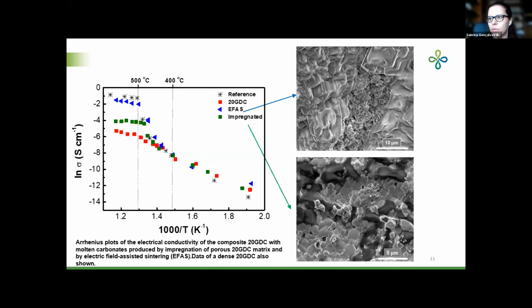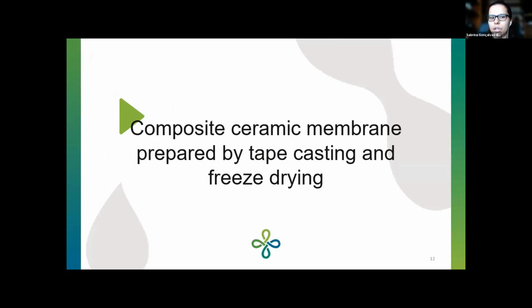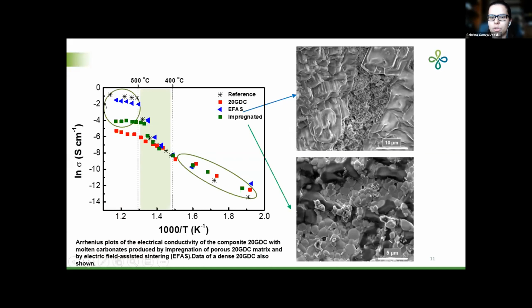And the ceramic pellets containing carbonate have dominant mechanisms depending on the temperature range. At temperatures below 400 degrees C, the conductivity is basically due to the oxide ions. From 400 to 500 degrees C, the electrical conductivity increases steeply due to the contribution of molten alkaline carbonates. And at upper temperature, the conductivity follows again an Arrhenius behavior, a situation ascribed to the carbonate and the alkali ions using the molten salt pathway.